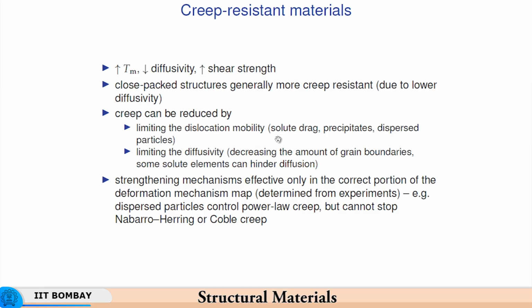limit dislocation mobility by introducing what is called solute drag, precipitates and dispersed particles, which will prevent the movement of dislocation. So, even at those high temperatures, the precipitates are the ones which will not get dissolved at high temperatures. Basically, these are precipitates like carbides of refractory materials, for example.